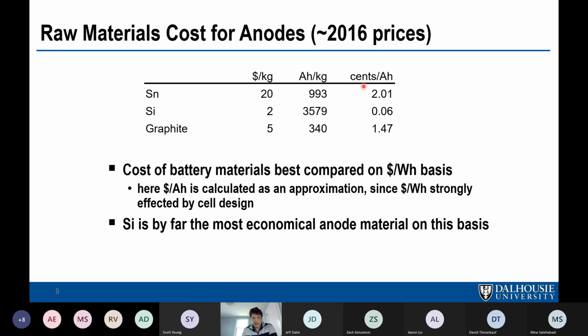And you can see if you calculate capacity, or I guess capacity normalized cost, silicon is by far the most economical negative electrode material, even more so than graphite. It's only 0.06 cents per amp hour, as opposed to graphite, which is almost 1.5 cents per amp hour. And both are much cheaper than tin. So this is the main reason we focus on silicon.